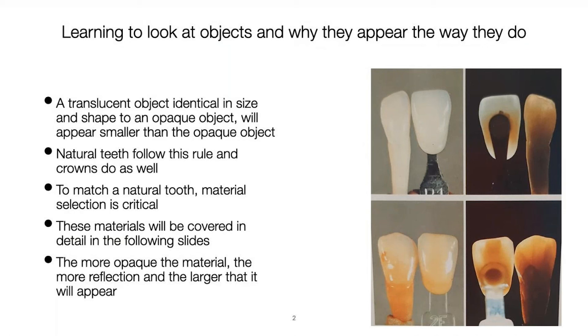The best color, scatter, and refractive index is actually found in plastics, because the particle sizes of the glass fillers don't have to change — you don't heat it up and melt it. That's why some people say you can't fire porcelain too many times: you're basically eliminating the glass and forming more of a crystal phase, which leads to cracking. This is called devitrification — you're de-glassing it.